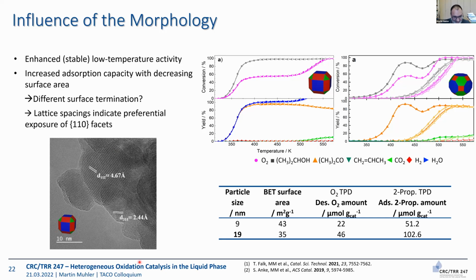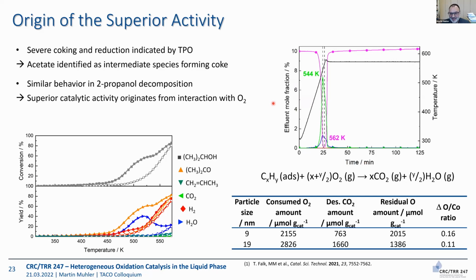Whether you can really identify facets based on TEM images, that would be a talk in itself. This is just a clever guess. We assume that we have more of them because we have larger particles, but we have not really solid proof for their presence, except that we have this very different stable reactivity. And now the question is, why is it more stable? Is it the interaction with 2-propanol that is different, or is it the interaction with oxygen that is different? And when we perform this heating in 2-propanol only, then we get the same profile that we have seen before. So it's not the interaction with 2-propanol that is different, but it's the interaction with oxygen.